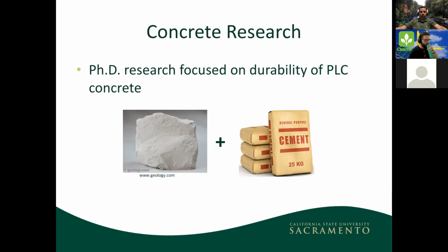Okay, so the question is, well, can we push that? Can we push the envelope more? Instead of limiting ourselves to 15%, can we go to 20%? Can we go to 25%? And then in addition to that, what my project focused on was the addition of supplementary cementitious materials, the stuff that would otherwise end up in a landfill. Can we also throw some of that in there because it was already making concrete better and stronger before? So can that work in conjunction with the limestone to make a good, high quality product and reduce the cement content? And the answer that we got was yes, we can still get a very good product using 50% of the cement that we were using before.